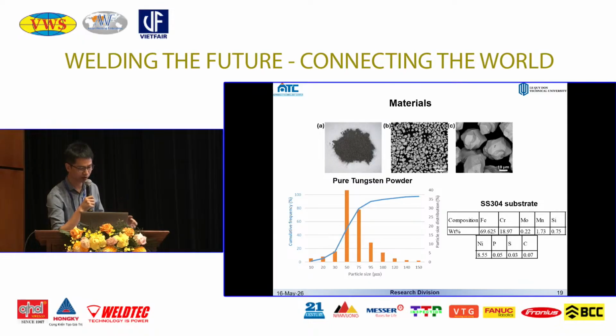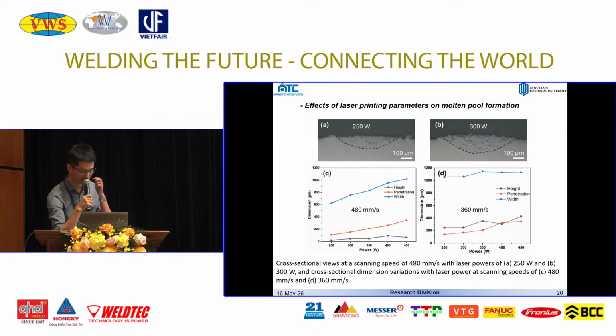Let's talk about the material. We used pure tungsten powder with a particle size of around 50 to 75 micrometers, and the substrate is stainless steel SS304. These are some very first results. We varied the laser power and cut the sample to see the inside structure of the printed layer, and we can see that the bead dimension increases when the laser power increases, of course. But when the scanning speed is smaller, the volume density is higher, and the beads become larger and unstable.